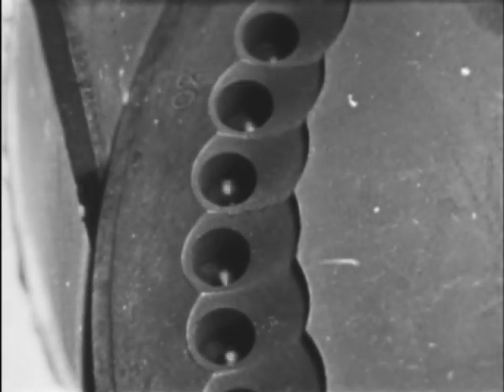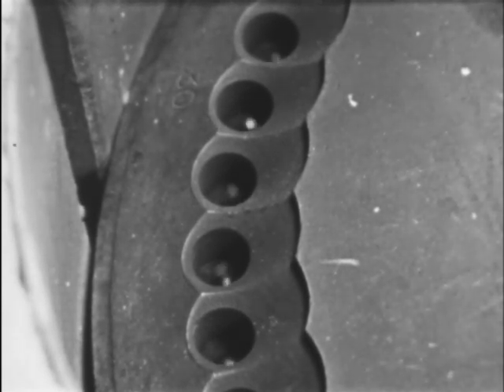An uninterrupted sodium bond is required between the jacket and the fuel for heat transfer. Voids are eliminated and sodium wetting established by heating the fuel rods as they are tapped from the bottom. Checked by eddy current inspection, the acceptable rods are reassembled into fuel elements.